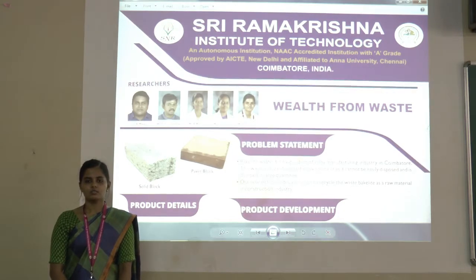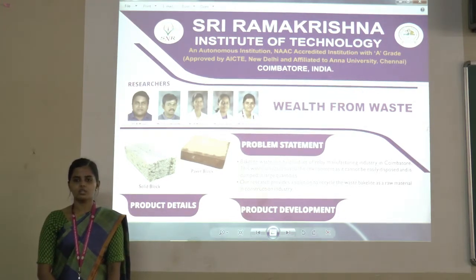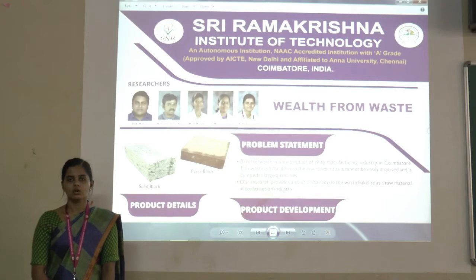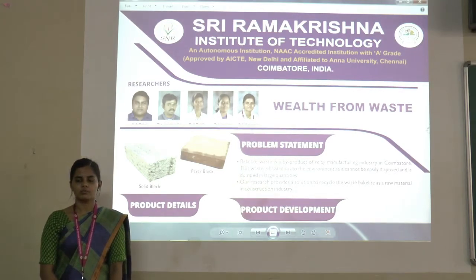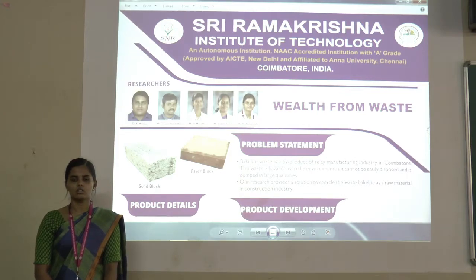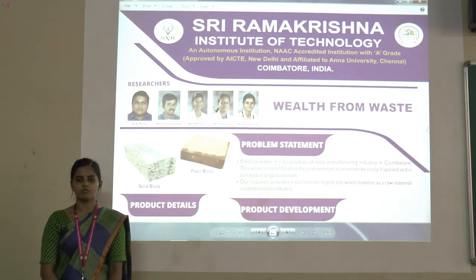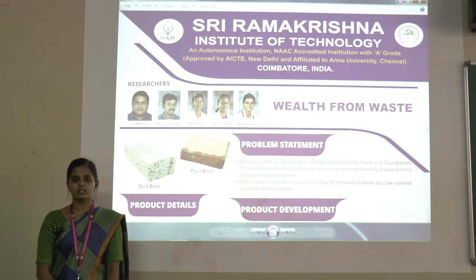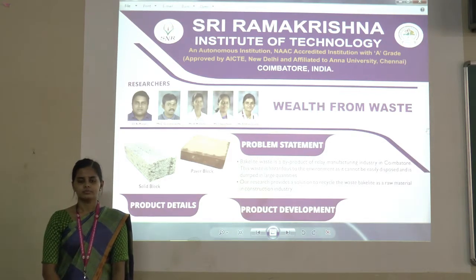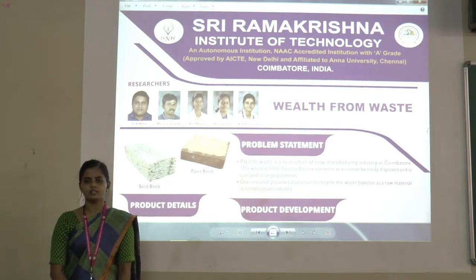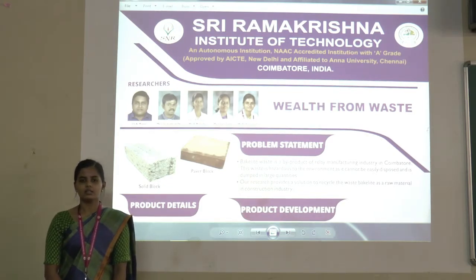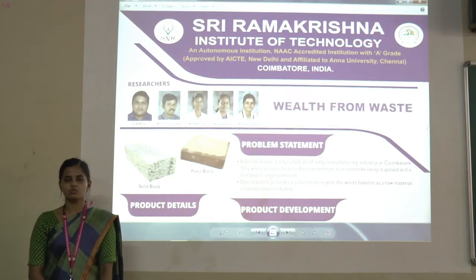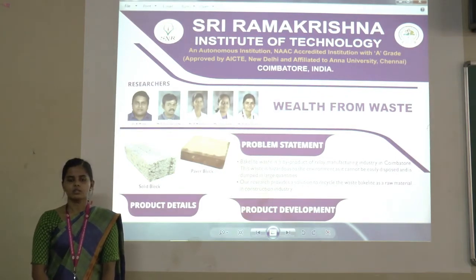The bulk density of the solid block used for load bearing unit should not be less than 1800 kg per meter cube. From the present study, it was noted that the bulk density of the solid block at the partial replacement of 10% was 1983.56 kg per meter cube. So it is clear that the required bulk density has been attained and the corresponding water absorption was 4.71%.